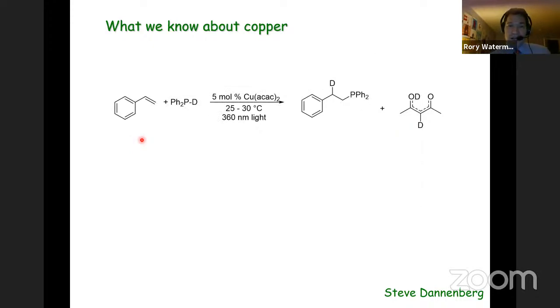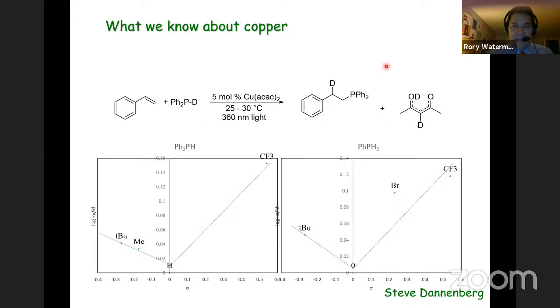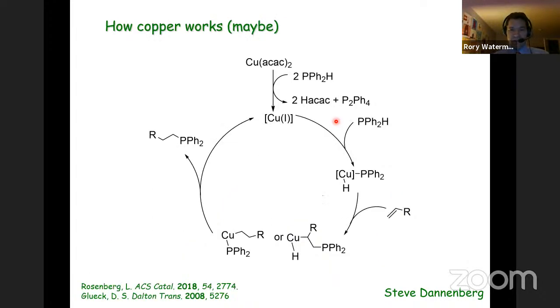We can deuterate at the phosphine, and we see very selective deuterium incorporation at the product. So that works exactly as expected. The deuterium is a little bit more complex on the ACAC, but that's a slightly different problem. We see an inflection when we do Hammett studies. So electron donating substituents on our substrate phosphine give us one dependence, whereas electron withdrawing groups give us the other, and same thing with the primary. The inflection to us is an indication that we're seeing a change in mechanism. And I'll explain that actually in the cycle that I have proposed here.